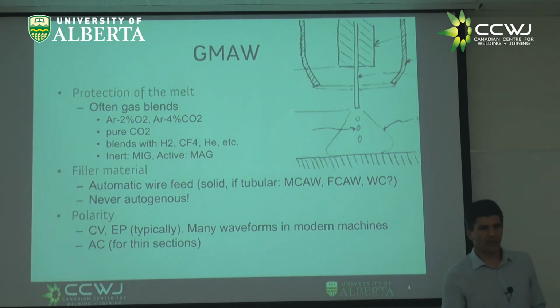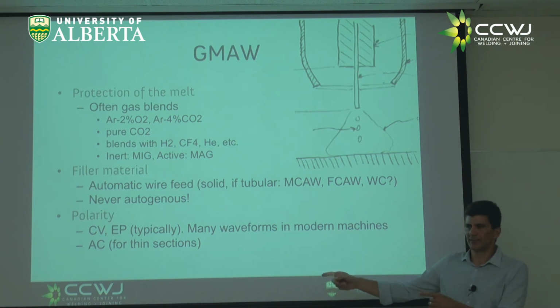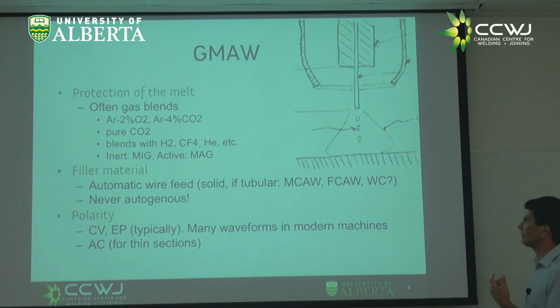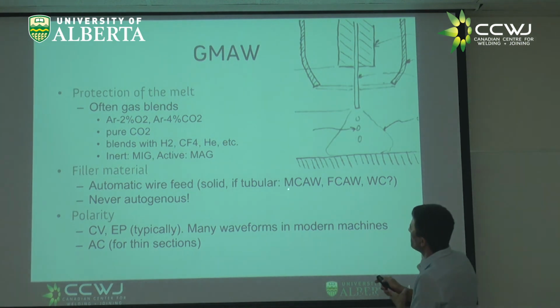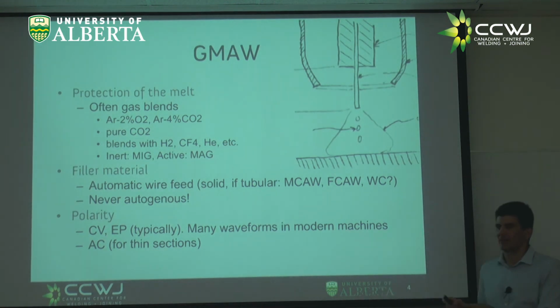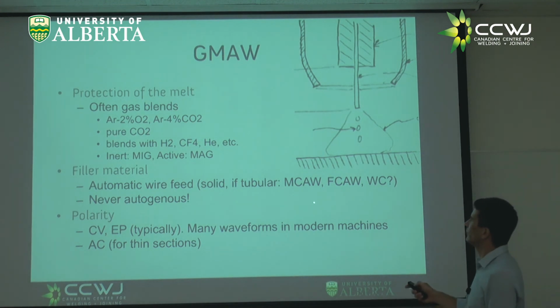But also, now you can play games. How about if instead of having a solid wire, I make a tube? We have the technology of making the tubes, and the tube can be steel. And inside I can put lots of chromium, and all of a sudden I'm making you a stainless consumable without having to cast like 50 tons of stainless steel. So many advantages. In that case, now it's called metal core arc welding. But it's the same thing. It's just that the wire, which looks just the same, is a very thin tube instead of being solid.